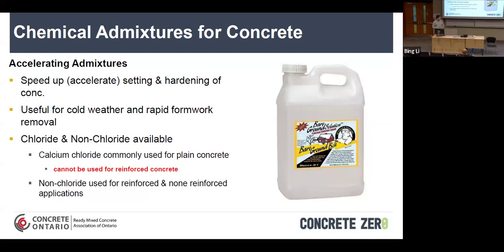Okay. It helps in two ways. One, it will speed up when that set time occurs. Let's say that they're trying to get traffic on the 401. I've actually done a job like this. We're trying to get traffic on the 401. That concrete has to set within an hour or two before traffic goes on top. So you need to set it up in an hour or two. You'll add an accelerator. Concrete doesn't naturally set up in an hour or two. If you're doing it in cold weather, again, the same thing, it will help you adjust that set time so that it sets at a normal time rather than delayed or accelerated.